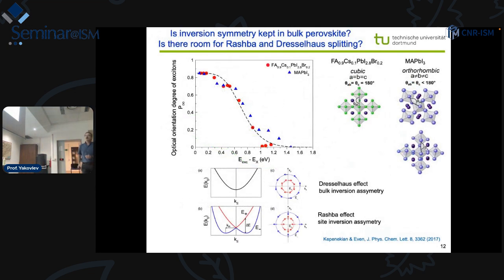Another thing which we also check here. So this is again the optical orientation degree as a function of the detuning. We have no spin relaxation for these materials, no decrease of optical orientation degree up to half an electron volt. That means that there is no spin splitting. And this spin splitting is a point which is discussed quite broadly in the perovskite community, the so-called Rashba or Dresselhaus splitting. Actually, the effect comes due to the strong spin-orbit interaction.